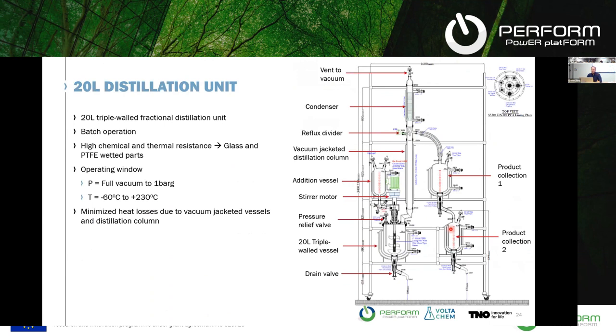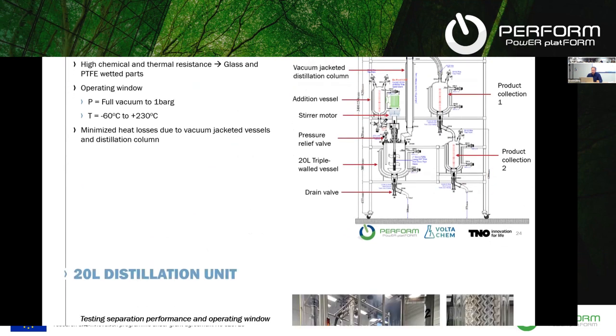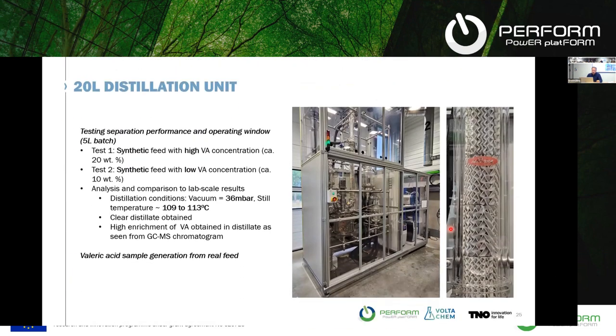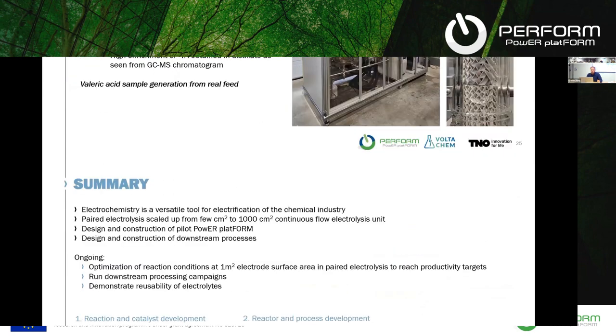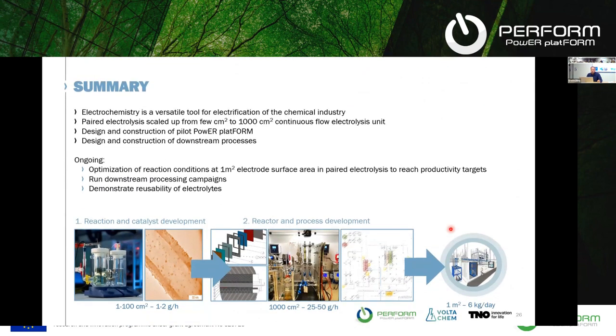We have a 20-liter distillation unit in-house where we can do this separation. Here you also have a picture of the unit, and we again tested with synthetic mixtures of valeric acid. Again, we can recover very pure samples of valeric acid. And with this, I would like to conclude about line one of Perform.